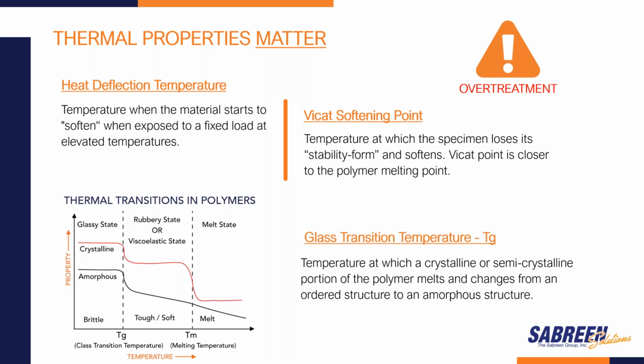This is the temperature when the material starts to soften when exposed to a fixed load at elevated temperatures. We also look at another property that's on the technical data sheet, and that's referred to as the Vicat softening point. The Vicat softening point is the temperature at which the specimen loses its stability of form and begins to soften. One of the things that you'll see is that the Vicat softening point is closer to the polymer melting point.